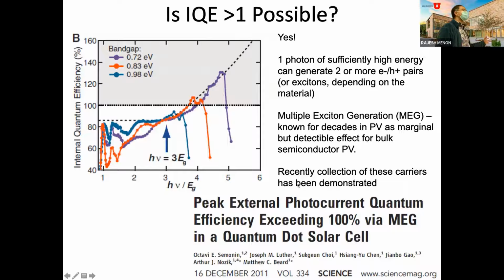They were able to collect these carriers more efficiently to show that you could increase the current. Now, of course, more electron-hole pairs means you're getting more current. That's really what you're looking for, at the same voltage, right? Since current times voltage is power, that means you're getting more power, obviously. So this is showing the internal quantum efficiency versus the energy of the photon. This is the energy of the photon relative to the band gap, h nu over Eg. Eg is the band gap of the material.